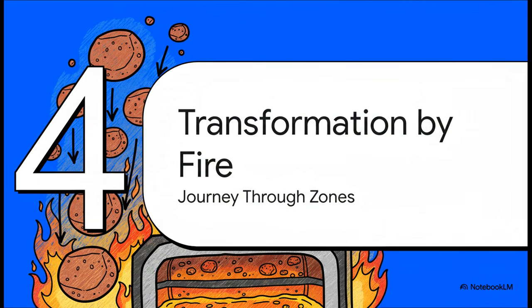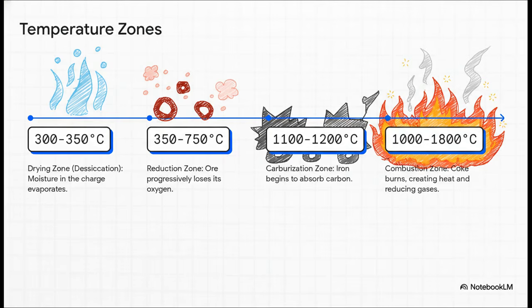Okay, now for the fun part. Let's imagine we're following a single chunk of iron ore on its journey down into the belly of this beast as it passes through hotter and hotter, more intense chemical environments. So as our little chunk of ore starts its descent, it first hits a drying zone at around 350 degrees Celsius, where any moisture just boils away. Then, as it gets hotter, the really critical reduction phase begins, and the oxygen starts getting stripped off. Lower still, the now spongy iron starts soaking up carbon from the coke. And finally, way down at the bottom, in the hottest zone reaching 1800 degrees, the coke itself combusts, providing that intense heat and the gases that drive the entire system.